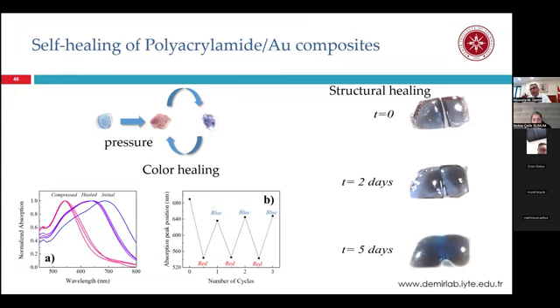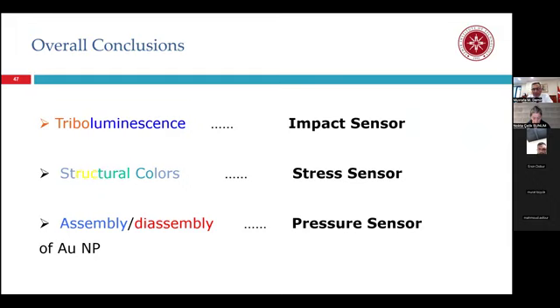Polyacrylamide is a self-healing material. We cut it into 2 pieces and put them in a humid environment. It swells, and these 2 pieces of polymeric structure merge with each other. They start to establish the hydrogen bonds again, and it returns back after, say, 1 week. Okay. So this colorimetric change occurs one after the other. After 3 cycles, we have almost the same blue color and the same red color after application of pressure, and it is a self-healing material. I think my time is running out.